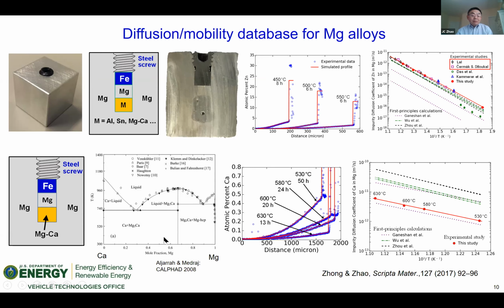So this allows us to make a measurement for calcium in magnesium. There's no isotope that can do the job. And calcium is very hygroscopic, right? It's hard, and the solubility is so low that it's very hard to make an alloy to diffuse against it. So we put in an intermediate amorphous alloy and let the liquid diffuse against the solid. You can see the solubility is 0.8 atomic percent, very low. So we were able to get, for the first time in the world, calcium diffusion in magnesium, because there's no data.